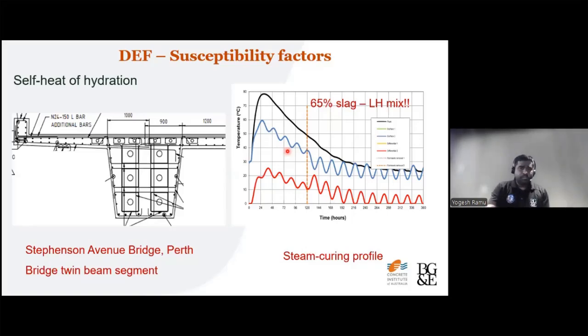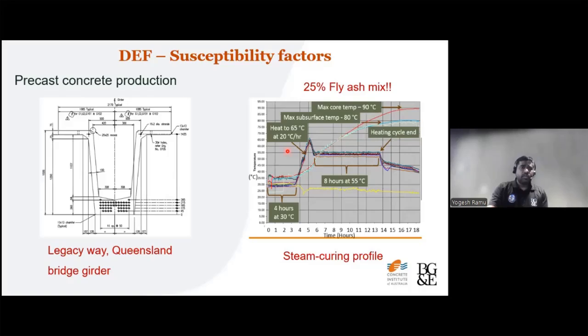Another example I want to point out is from a precast concrete producer in Queensland. These bridge girders were manufactured for the Legacy Way project. As you can see on the left side, the precast girder is very deep, roughly 2 meters, and the concrete had a 25% fly ash mix in it, but still it went up to 80 to 90 degrees Celsius when it was cured at 55 degrees Celsius. So high temperature in concrete is possible even when there are SCMs in it, whether in-situ or precast concrete production.